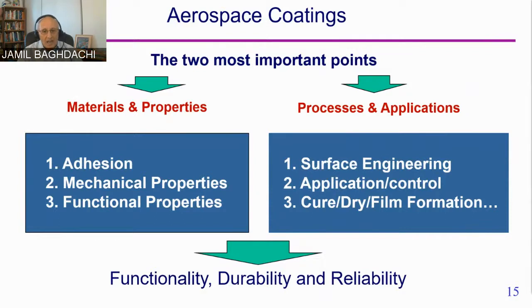And cure. At times I have found out that the paint has not been cured. If paint doesn't cure before you take it for flight, it is not going to cure anymore once it goes to minus 40 degrees, folks. So then the whole system falls apart, which, unfortunately, when we analyze it, we figure this out. It happens. Next slide, please.